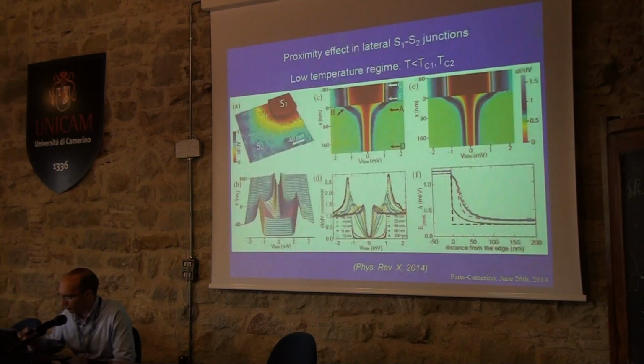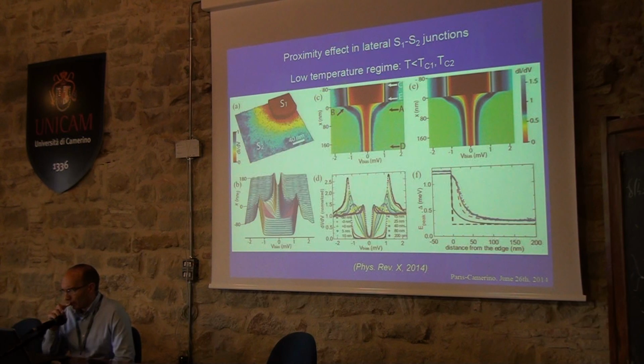So, next slide, please. On the left upper part, we plot a topographic image in which we have a superconducting lead island, a thick island that we call S1, with a superconducting critical temperature of 6 Kelvin. And on the bottom part, you have this crystallized wetting layer, which is superconducting below 1.6 Kelvin. So you have this lateral junction between two different materials, and you can play with temperature, and you can realize the situation in which the junction is type S1, S2, so you put in contact two different superconductors, or at a higher temperature, you may have the island still superconducting, but the wetting layer will already be in the normal state.